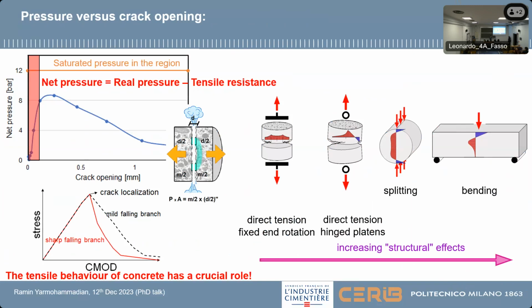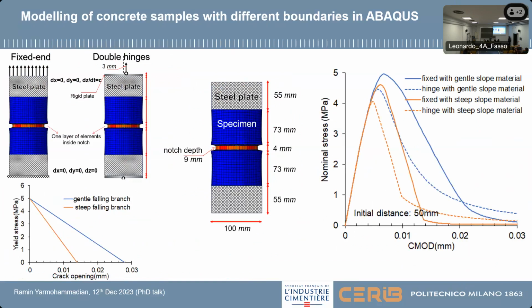While in direct tensile test, it is more related to the material behavior. So we think that the direct tensile test is better to understand what is the material behavior, and then we started to model again in Abaqus to understand how the boundary condition can change the behavior that we are assessing from the test. As you see, if we have two different materials, a simple one, gentle and steep falling branch, if we use two different boundary conditions, what we get from the test is completely different. So since now we need to get the real behavior of concrete, it's better to use the fixed one.